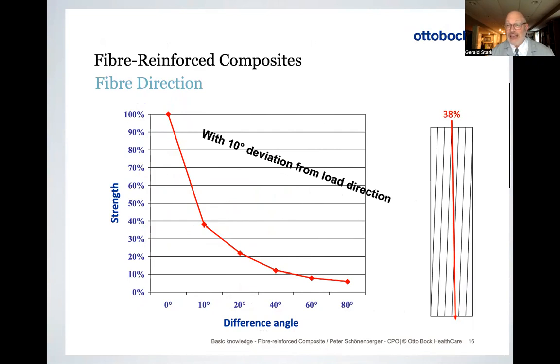So how do we accommodate that, or how do we get away from that? Well, we do multiple levels or multiple layers that provide us resistance. So we know that we're accommodating the range of motion. If we have 23 degrees of rotation, for instance, we need to accommodate those 2 different positions with the lower limb. So 23 degrees of lower limb movement in terms of rotation, we need to make sure we have fibers that can resist those extremes, or at least 80% of it.